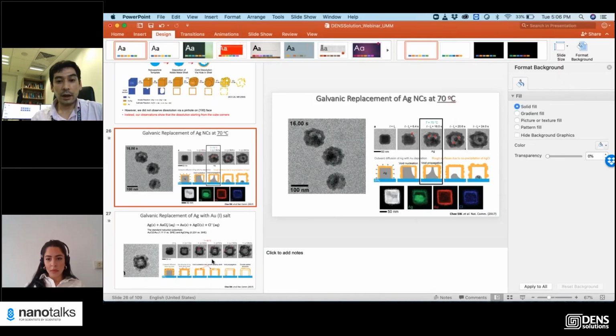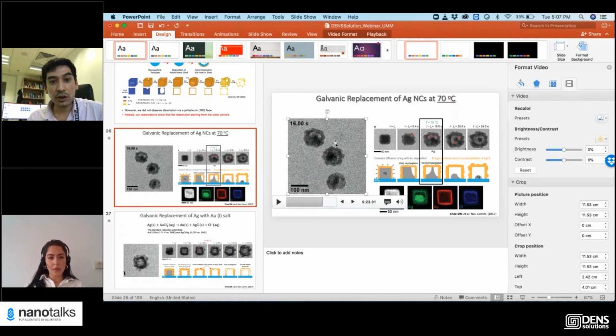Yes, the solubility of silver chloride salts is not high, and then you can see them precipitating. So the shell is not just gold, and not just gold and silver, but silver chloride is also present here. It precipitates out, because if you look at the elemental map, you do have chlorine, so it does not dissolve fully.